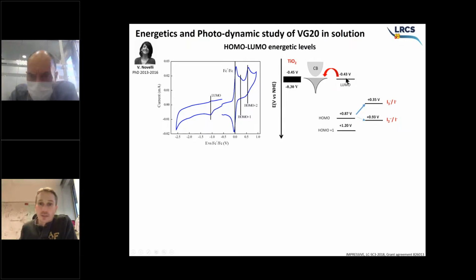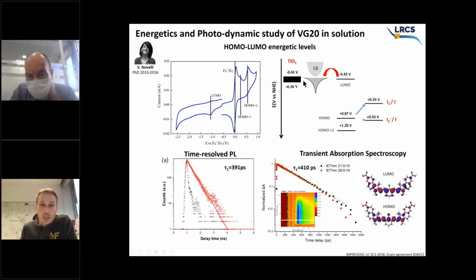This is the LUMO level, which is at minus 0.4 volt versus NHE, right at the alignment of the conduction band edge of the anatase TiO2 nanocrystals. We did a little bit of science about those molecules, especially in terms of time-resolved spectroscopies. So here is time-resolved photoluminescence, which showed that the excited state lifetime of those kinds of molecules is very short, 400 picoseconds. By comparison, a perovskite solar cell is microsecond timescale, and ruthenium polypyridyl complexes, which are the standard for dye solar cells, are about 10 nanoseconds.